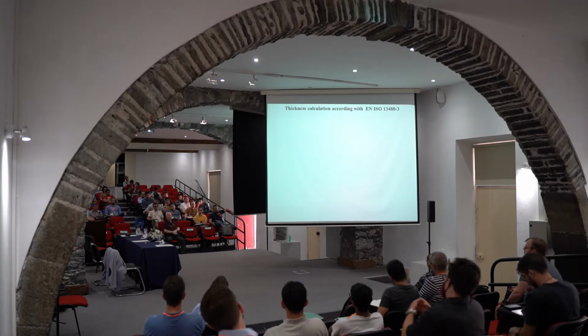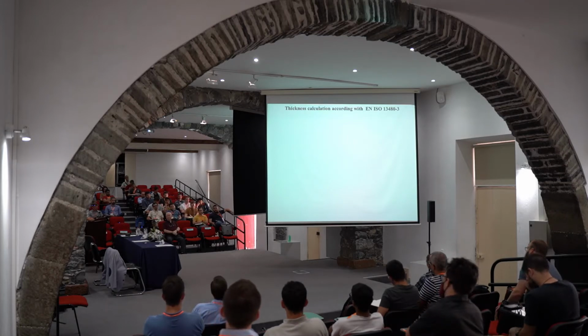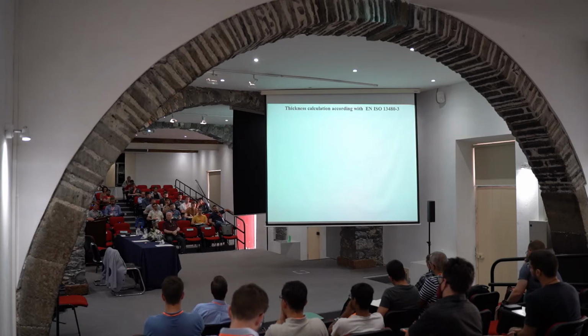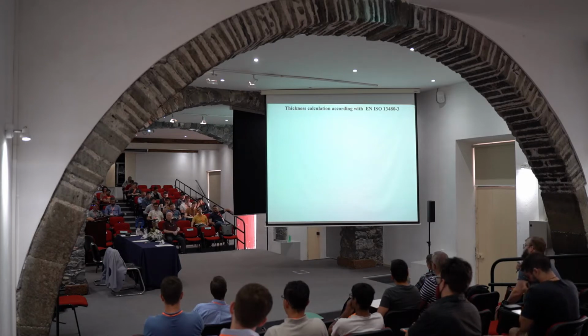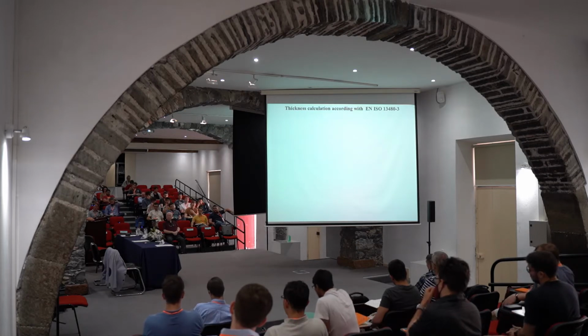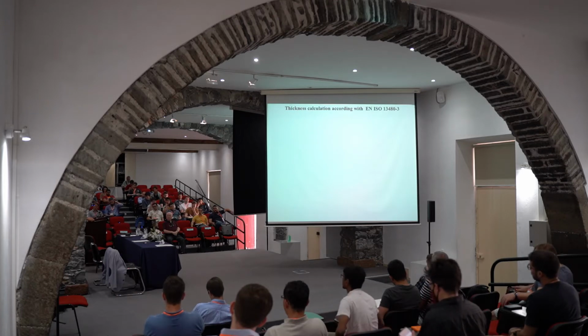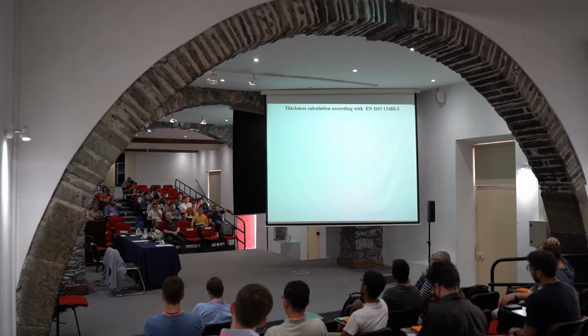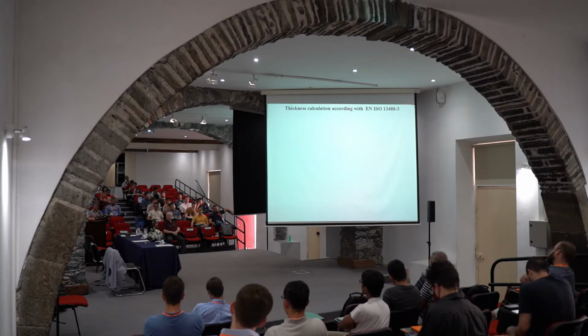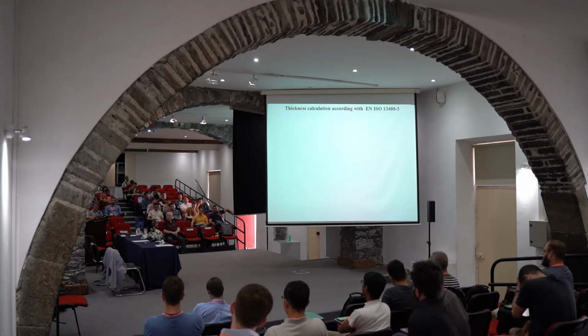What this slide shows are thicknesses that were calculated according to the standards, which indicates that in the case of this high yield strength steel, we still needed slightly more than 50 millimeters of thickness. Now the producer could not satisfy that condition. He would make 47 millimeters, and the decision was to still follow this line of thinking and this design, and to reduce so-called safety factors. That is, from the engineering and philosophical point of view, really important for further discussion.